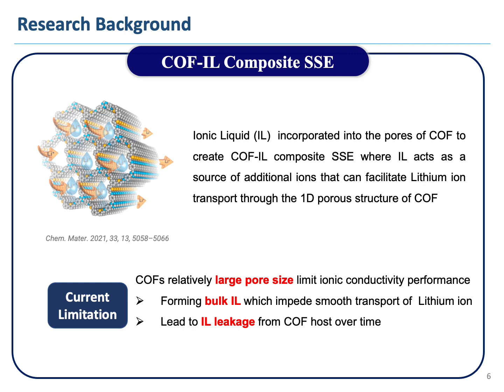Ionic liquid is a class of organic salts that are liquid at room temperature and possess distinctive properties such as high thermal stability, low vapor pressure, and good solubility for a wide range of salts. Using COF as a host, COF-IL form a combined phase of COF-IL composite that improves ionic conductivity and electrolyte interfacial compatibility through a wetting effect.